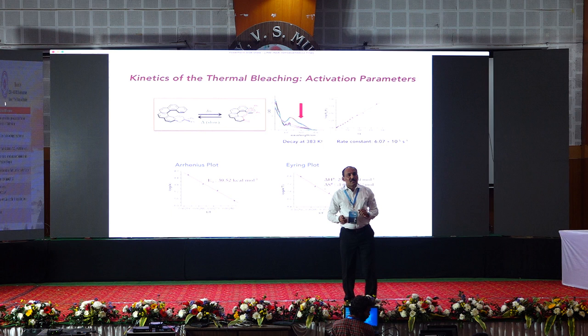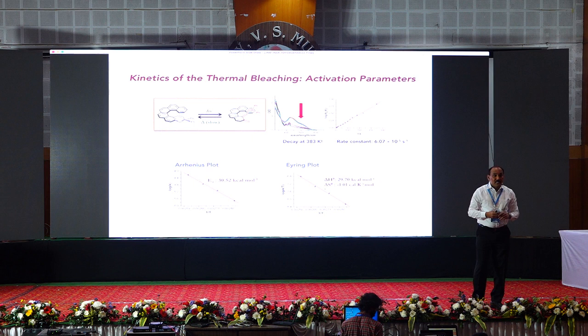Now, can I pose this question? It's all about molecules to materials I talked about. Can I now modulate the structure? What comes back at about 110 degrees, can I make it come back at 90 degrees? Can I make it come back at 70 degrees? Can I make it come back at 50 degrees? In other words, can I develop a series of molecular materials that revert at graded temperatures? And how do we do that? It's all about the helical scaffold. Can I worry about releasing this helical arc little by little by molecular design? Which is what we did here, right?